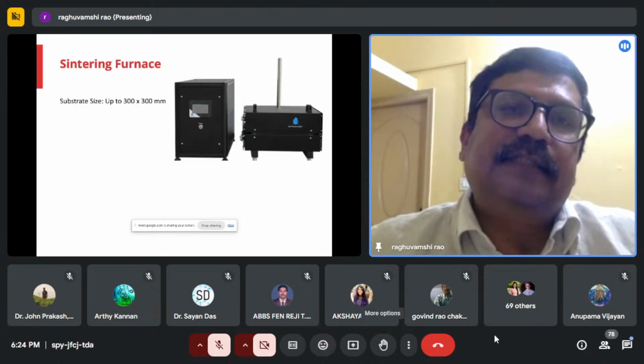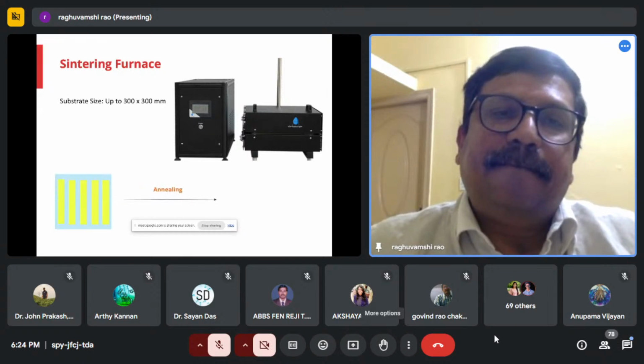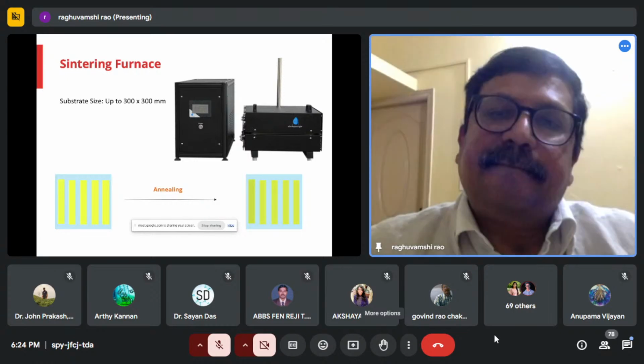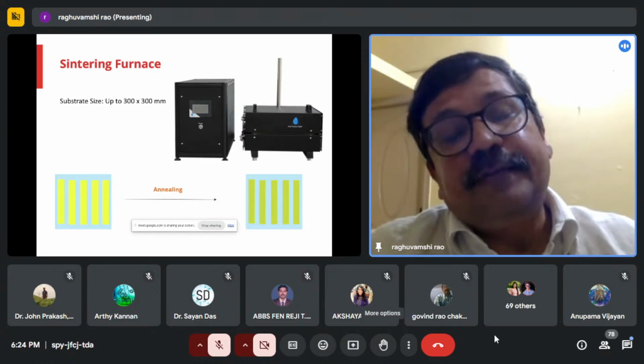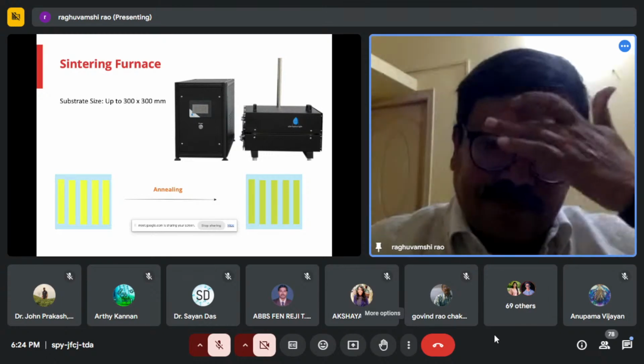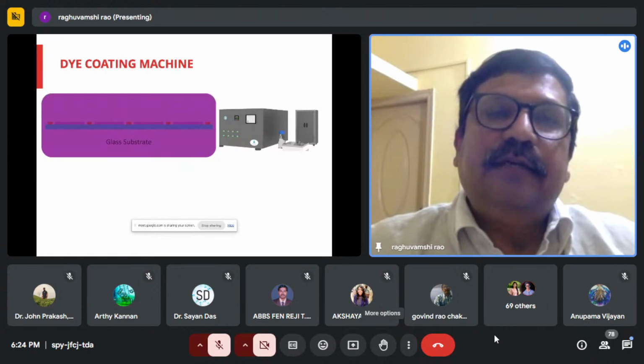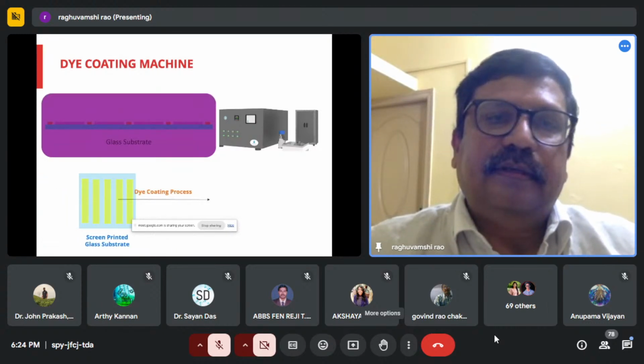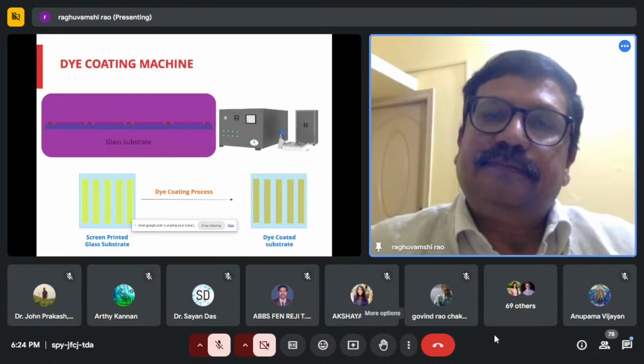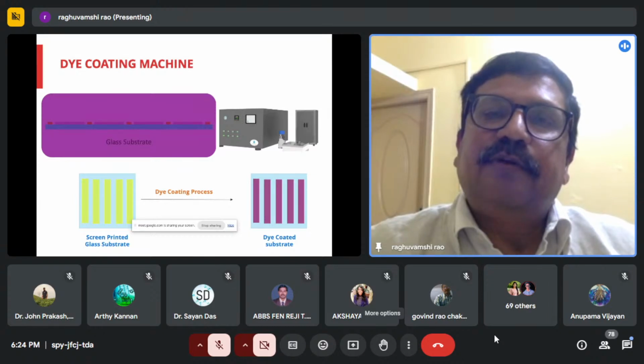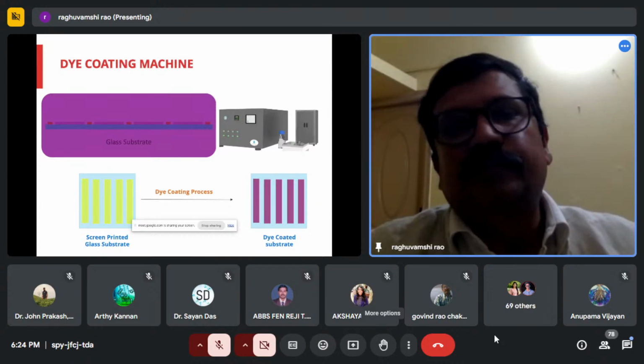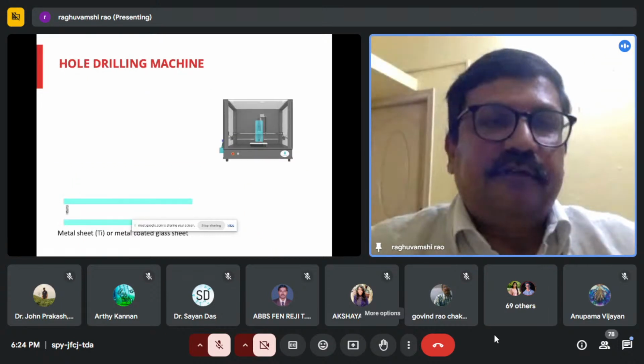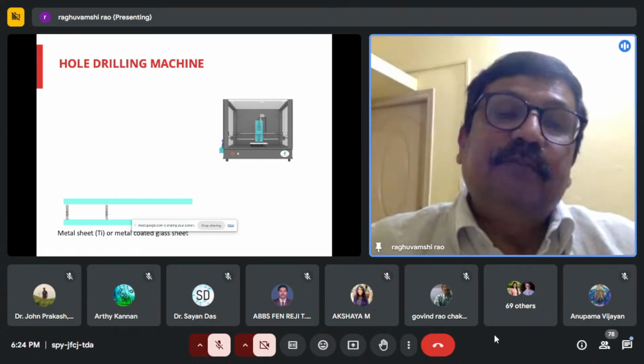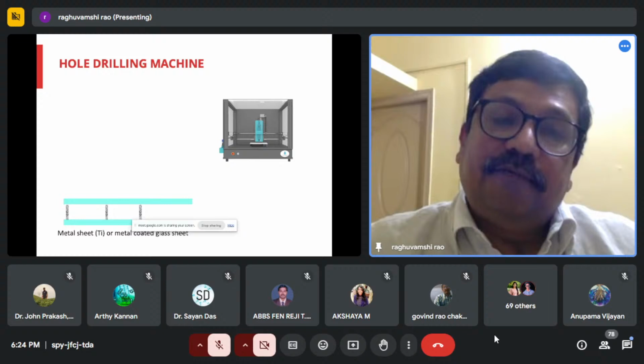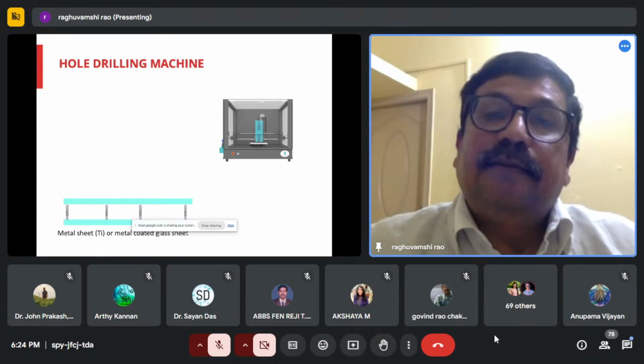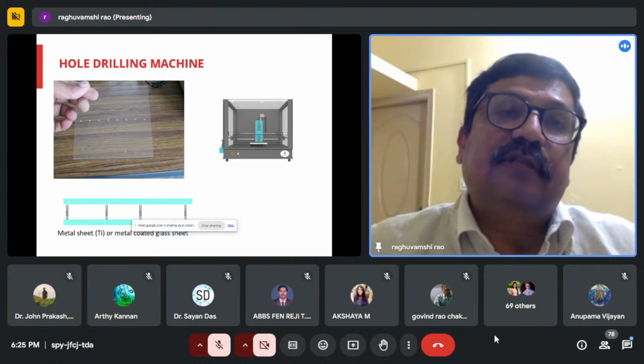We work on sintering furnaces of different dimensions. And we tailor it to different temperature settings with ramp and soak involved in that. Dye coating machine, automatic dye coating machines, where your semiconductor TiO2 coated units could well absorb the dye. We also have hole drilling machines on glasses, which we handle precisely without any chipping of glass. And then this is primarily for the electrolyte filling system.